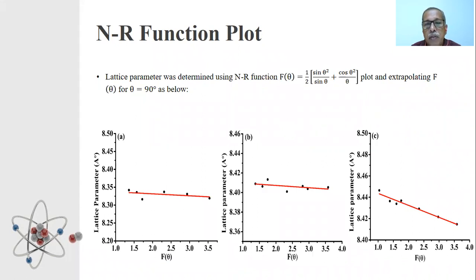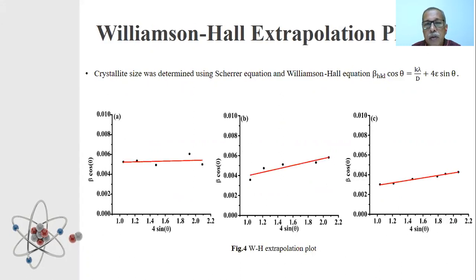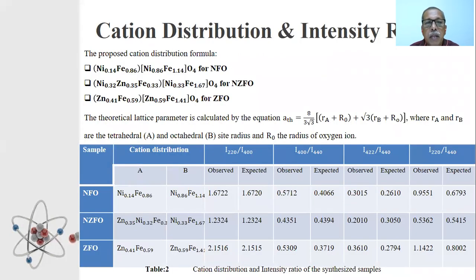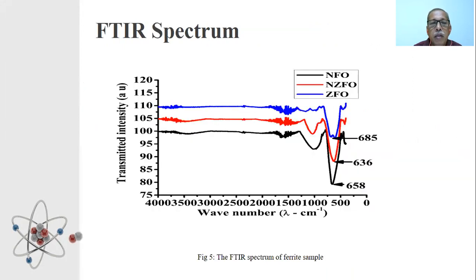The Nelson-Riley function plot is used for identifying the lattice parameter. The Williamson-Hall method is used for determining the crystallite size. It is observed that particle size ranges from 29 to 50 nanometer depending upon the material of choice. The cation distribution of the material is determined using intensity analysis of the diffraction peak. The intensity ratios of prominent lines observed and expected based on the cation distribution formula is tabulated here. The close agreement between the two confirms and supports the cation distribution formula.